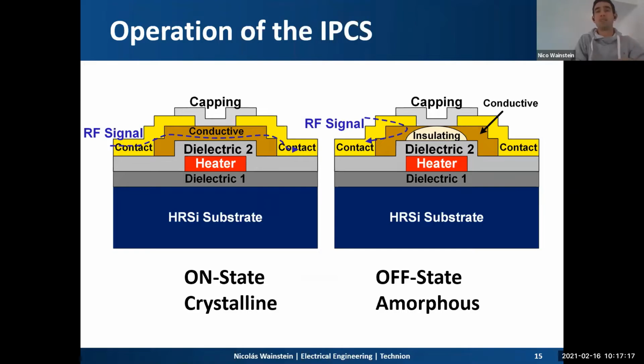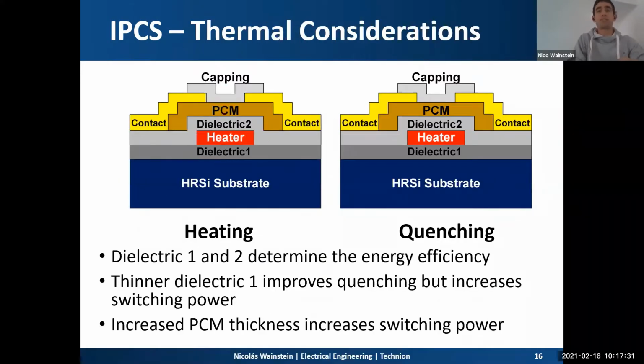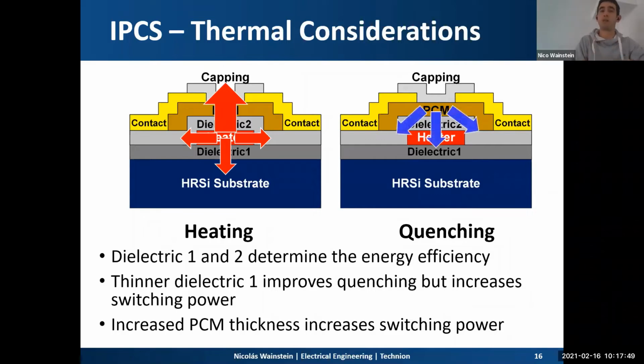When the PCM is in the crystalline phase, the RF signal flows between the RF ports. Meanwhile, when the PCM is in the amorphous phase, the signal is reflected back from the input port. The device, as I mentioned, is thermally actuated with voltage or current pulses at the heater. During programming, heat is conducted through the dielectric up to the PCM layer, and then it's dissipated through the contacts and substrate through dielectric 2 and dielectric 1.